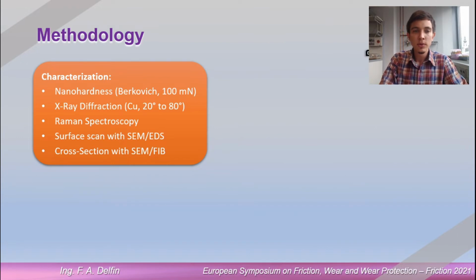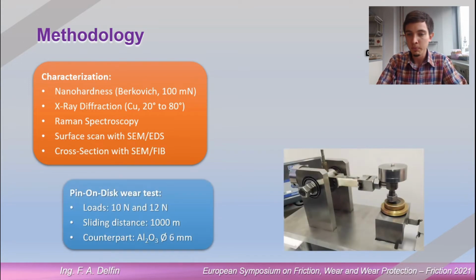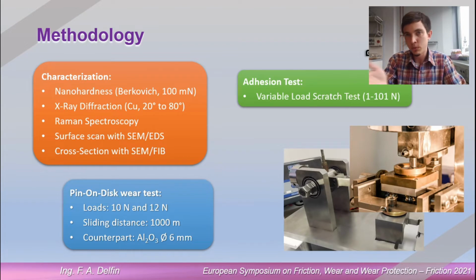We did some analysis with these samples: normal characterization, nanohardness, XRD, Raman. We scanned the surface. We also looked at the cross-section with the focused ion beam. And then we did some tribological testing with the samples using this pin-on-disc apparatus. It's homemade at our university. We applied 10 and 12 Newton normal load with a sliding distance of 1000 meters using an alumina counterpart of 6 millimeters diameter. And of course, we analyzed the wear tracks and friction coefficient and everything.